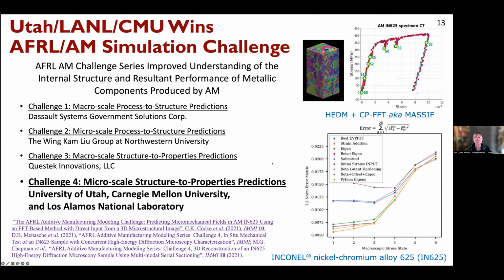We used their HEDM data, and we ran this FFT method, collaborating with Ricardo Lebensohn at Los Alamos, who's the origin of this, fitting the stress strain curve, and then comparing the elastic strains, full tensor, in each of those 28 grains against the measurements. And this error plot here shows you where we started.